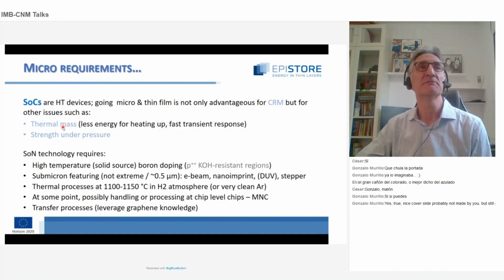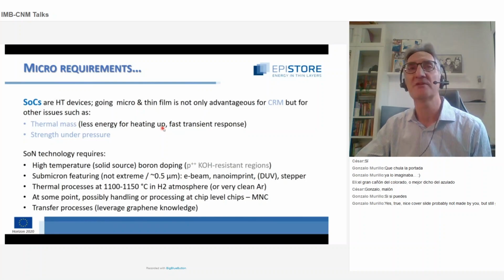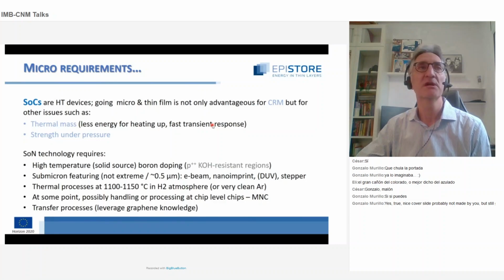So it's advantageous from a thermal mass point of view, because we will need less energy to heat up everything, and also the device will be able to follow fast transient responses, and this is very important for the application that we have in mind, especially if we are thinking of portable applications, and also because thin films exhibit, especially for ceramic materials, a higher strength under pressure, and these devices will be under pressure.